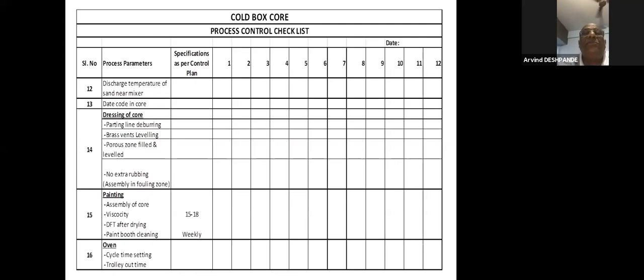Then discharge temperature of sand near the mixer. Discharge temperature is also important because the resin reaction is important; at around 30 to 35 degrees the exact correct reaction takes place. If the temperature of sand is below around 25 or 28, basically in monsoon, then for the same addition we get less strength. If you increase the temperature to 30 to 35, above 30, then we can get the correct strength. These are experiments done by me personally, and we have kept the record also. So this is most important.